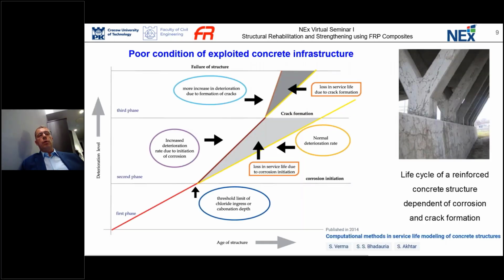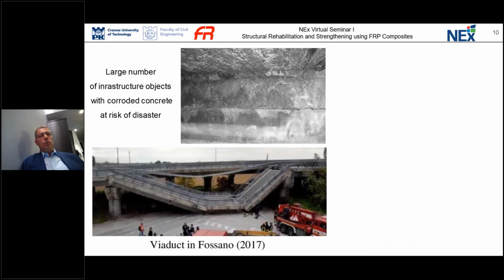Coming to the problems that we have with our infrastructure, we know that over many years, the structure starts to deteriorate, first by initiation of corrosion, then by formation of cracks. The life cycle of reinforced concrete structures is shortening, and in this case, we have to take into consideration the possibility of turning off this kind of structures and stopping their exploitation. So to be able to use them longer, we should think about some improvement. Of course, if the structure is seriously corroded, it can cause sudden damages, like the viaduct in Fossano in 2017, where very corroded concrete was the source of this catastrophic event.